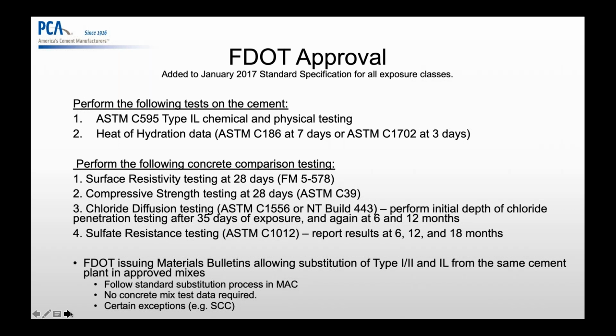to the FDOT with the reporting requirements, heat of hydration as well. And also on the concrete, there's a plethora of testing that must be performed and must comply with the specification in order to have the cement approved by them, like surface resistivity, the compressive strength, chloride diffusion, sulfate resistance, and so on. So once those tests are reported to the agency and they approve it, then the FDOT issues a material bulletin where you can substitute a Type I/II cement for a Type 1L on the governmental projects.